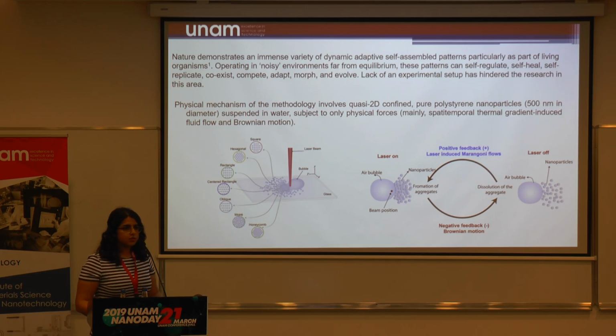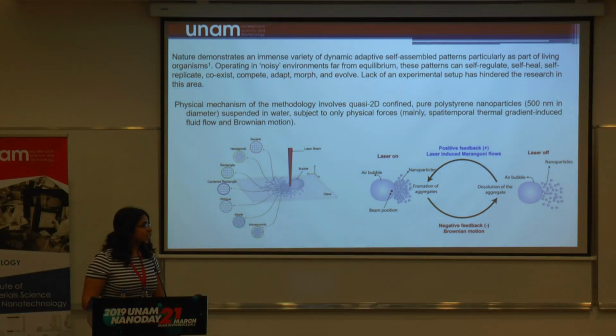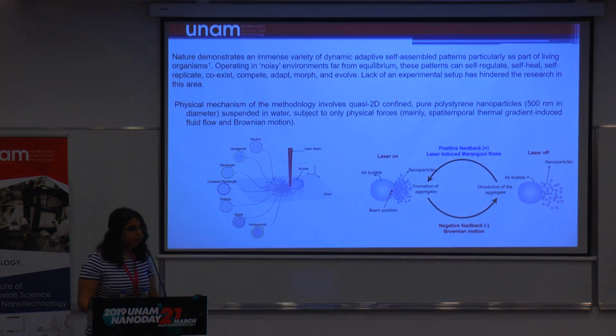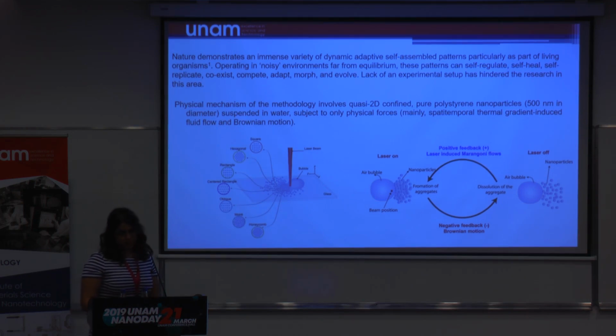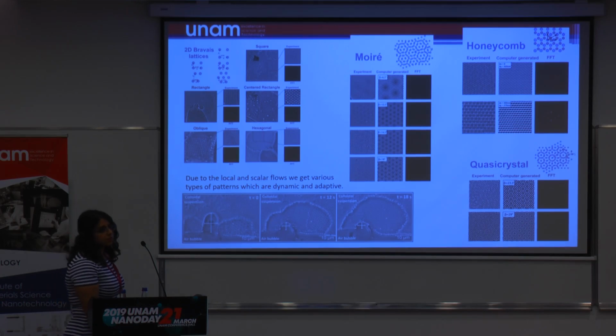The laser-induced Marangoni flows and Brownian motion of the particles will create a feedback loop. As long as the laser is on and we have the Marangoni flows, we will create aggregates, and as soon as we turn the laser off, the aggregates will dissipate due to the Brownian motion of the particles. We were able to observe all the 2D Bravais lattices and more complex moire and honeycomb structures. These are our experimental results.